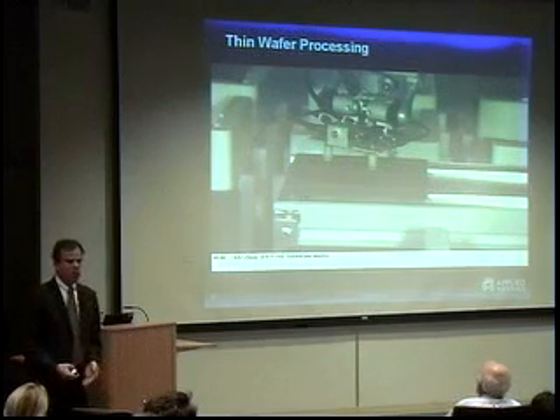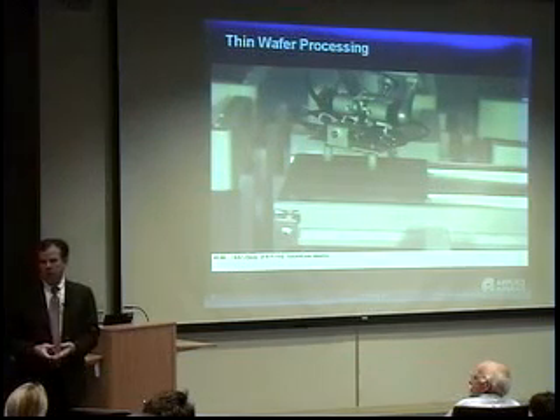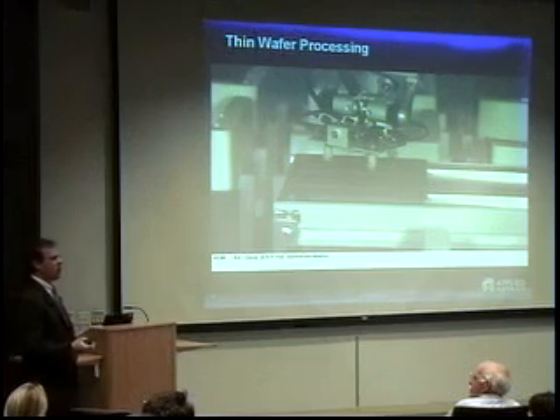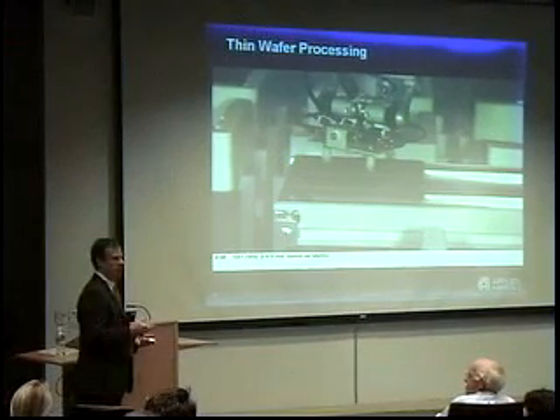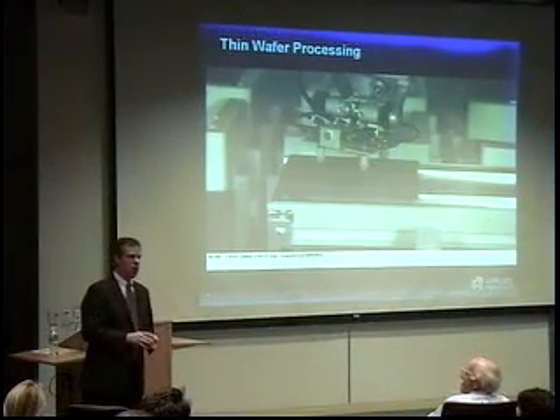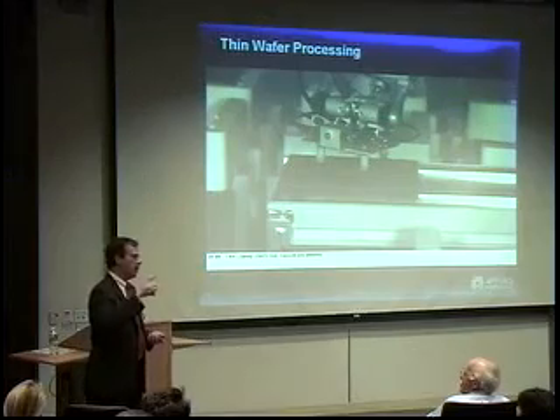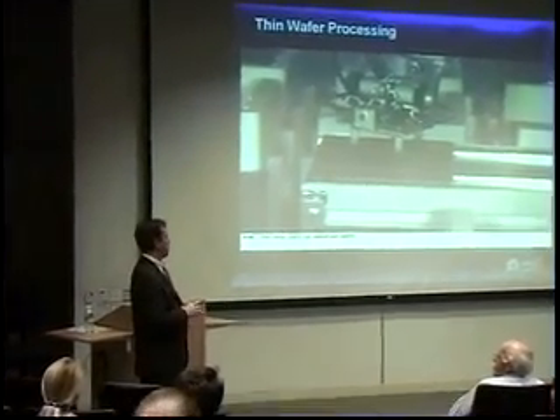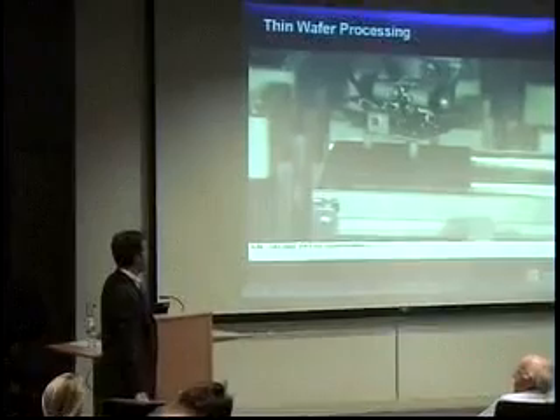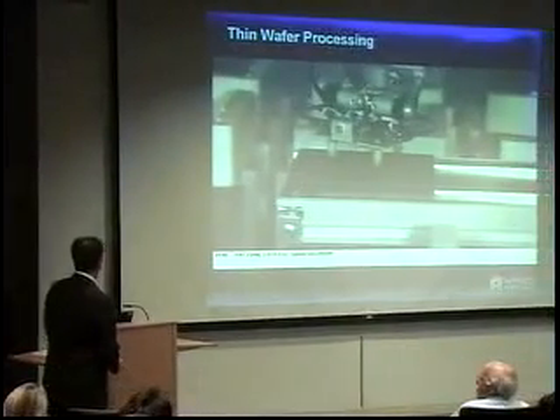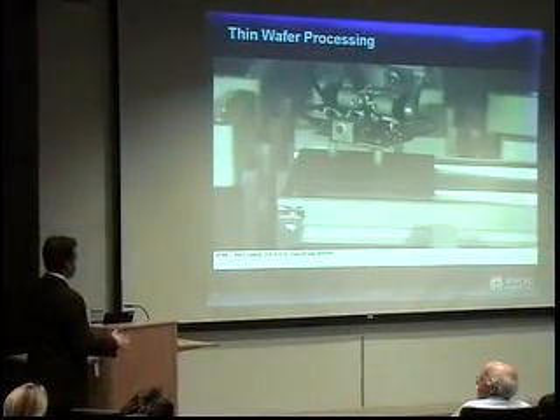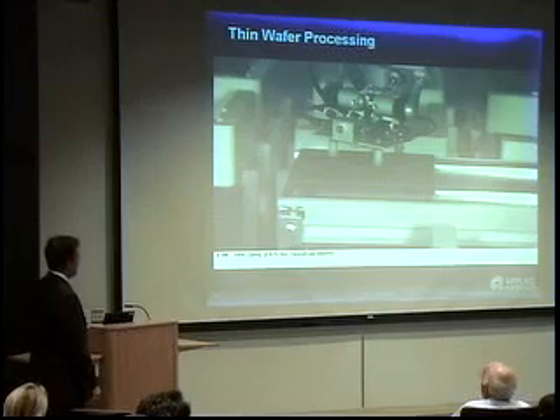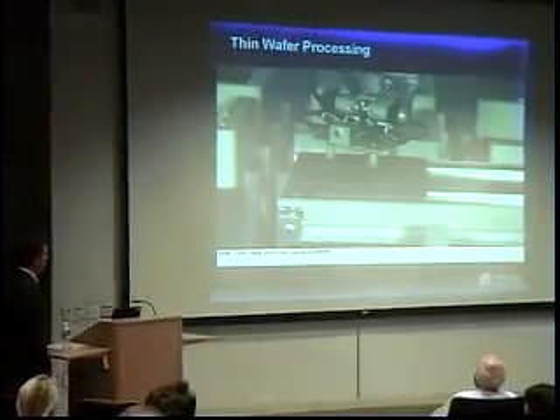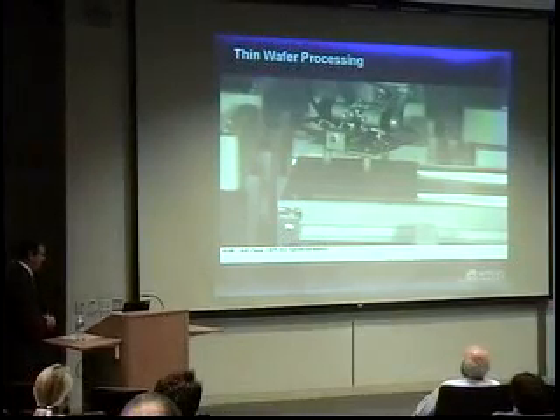Once you have these thin wafers, now you want to go and make solar cells out of them. You put them in a line. It's not so simple. Thin wafers, in semiconductors we use wafers that are hundreds of microns thick, and they're single crystal, they're nice and strong. I'll just show you a little video. This is a slowed down camera. I think this is a 200 micron thick wafer. The speed is going to be 400 milliseconds, and you'll see why these are a challenge to deal with.